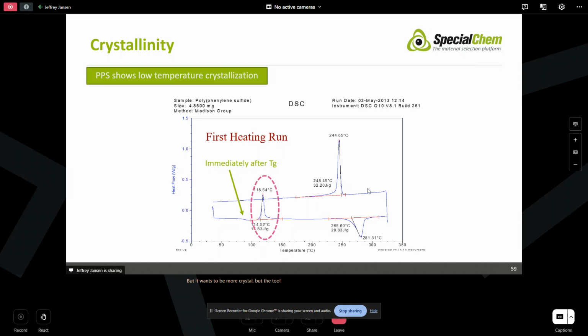But the tool used to mold it was probably relatively cold. Perhaps the molder wanted to produce more parts per hour and didn't really focus on crystallinity. Again, this tells us that the material has been undercrystallized. In fact, if we look at the heat of crystalline formation, it's about 15 joules per gram. When we look at the melting of all the crystals, both that were there before and those that formed during the test, it's 30. That tells us that half the crystals that are melting during this test were formed during the test itself. The material was only, if you will, half crystallized during the molding process. Again, that has severe implications for its performance properties.